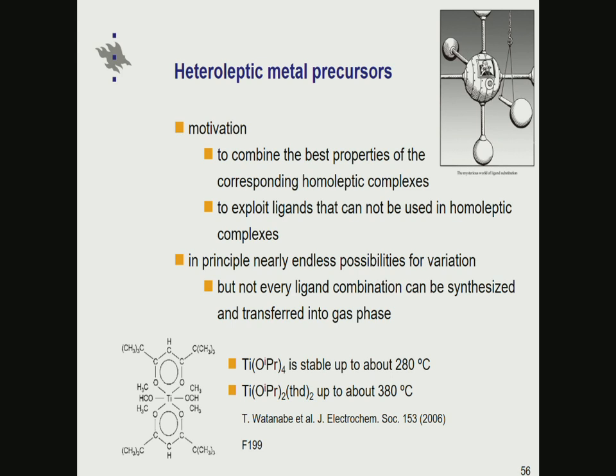So you may be able to make certain heteroleptic metal compounds, but once you start to heat them, there are ligand exchanges which actually break them down to the homoleptic compounds and so on. But one example shown here is titanium isopropoxide. That's reasonably stable. 280 has been quoted as a limit in this case. If there is a desire to go to higher temperatures, by changing two of these isopropoxide ligands with THDs, producing this kind of molecule, you gain 100 centigrades in thermal stability. On the other hand, at this point there is the addition of these beta-diketonates, which are not so reactive with water molecules. Most likely, we don't have our own experience on this compound, but most likely you are losing at the same time in reactivity with water.